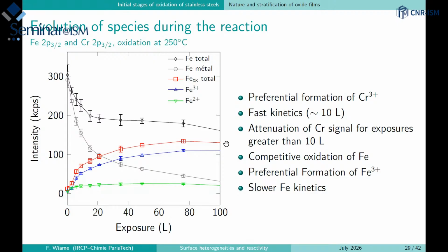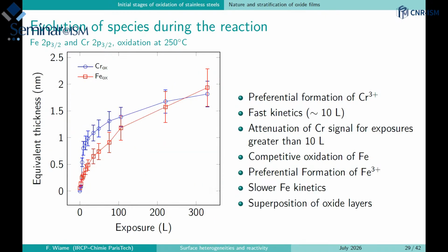And so we have initial preferential formation of chromium 3+ oxide, but it will continue above the iron oxide. If we are calculating the thickness of this chromium oxide and iron oxide, we can see that in fact the chromium oxide is increasing very fast. In a few Langmuir, you already have 1 nanometer thick chromium oxide. The iron oxide is increasing much more slowly, but it will continue for a much longer time, while the chromium oxide is saturating very rapidly.